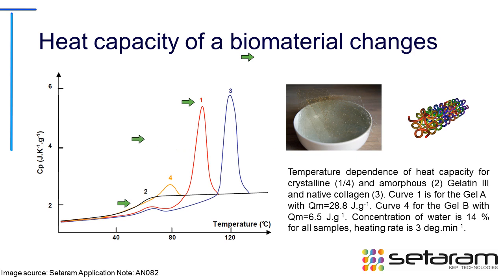We need to measure them because they can have a change through the processing of gelatin. So after we melt, we see that the heat capacity does not change over time, whereas in the first run, we see a huge dependence on temperature for the heat capacity of the material.